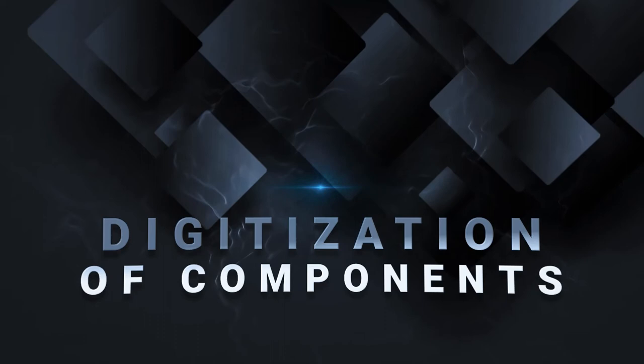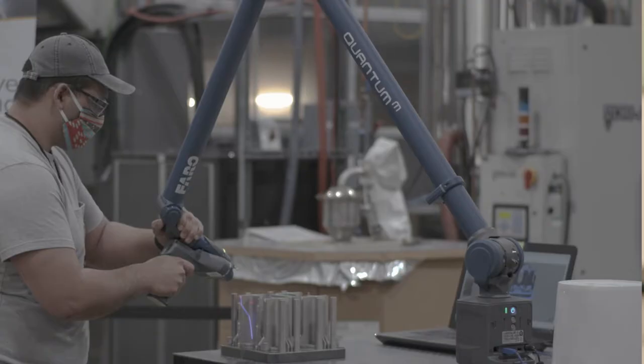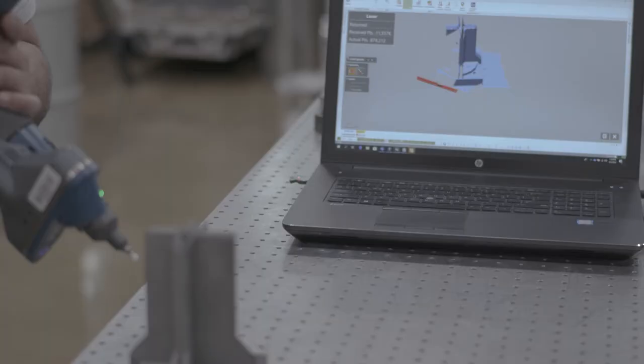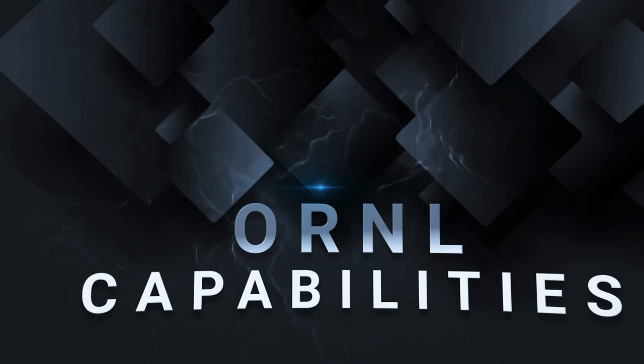One of the most significant outcomes is what we're doing on the digitization of the manufacturing process. We've created a mechanism to take images of every single layer that we print during the entire process, which are transferred and digitally analyzed using artificial intelligence-based software. It gives us an understanding of every single defect that could possibly be in that component in three-dimensional space. We can couple that information to the actual end inspection and characterization of the component.